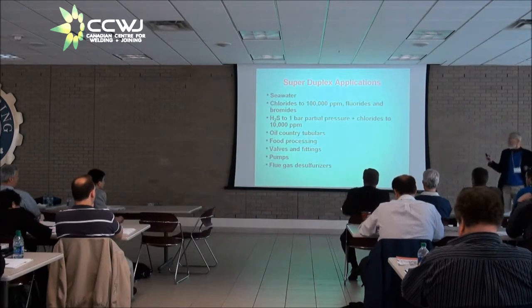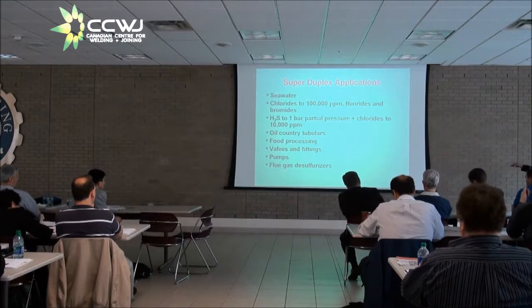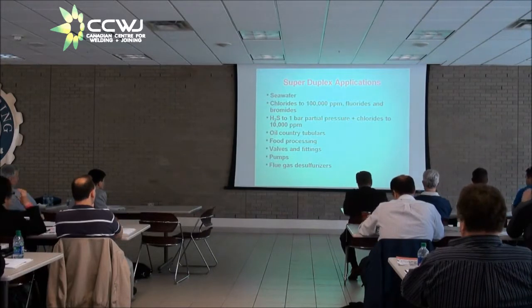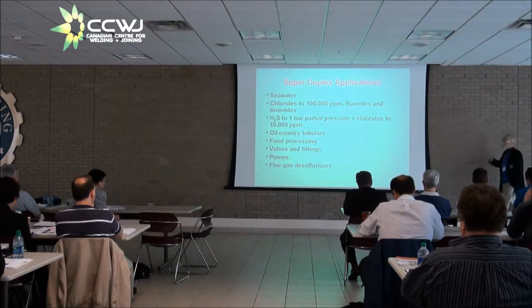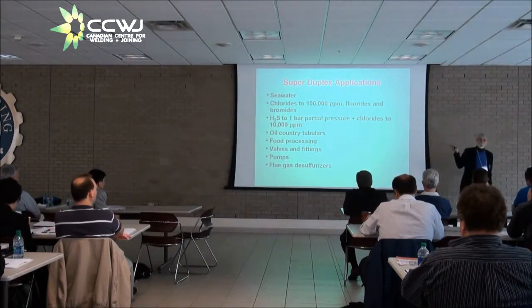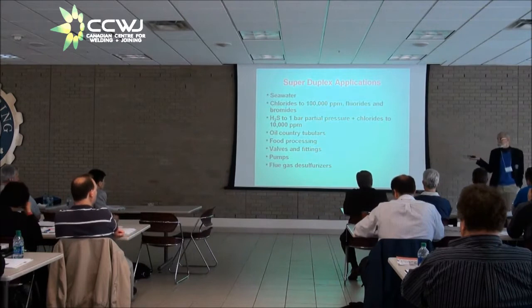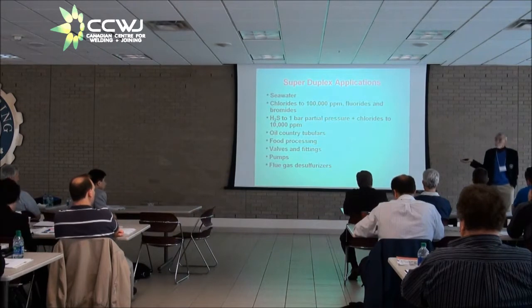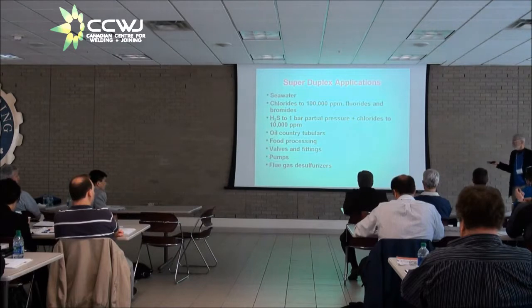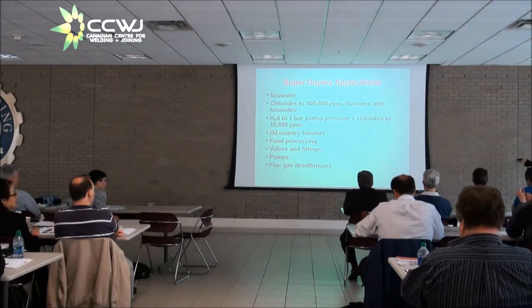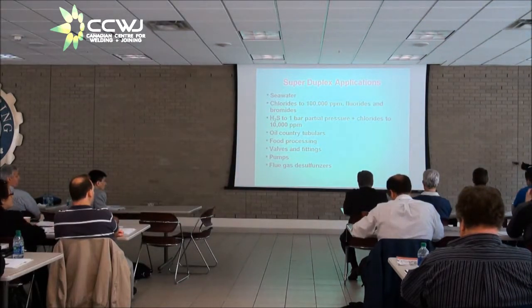One of the interesting applications for the super duplexes is the flue gas desulfurizers. Flue gas desulfurizers have high temperature areas and low temperature areas. You don't use super duplex in the high temperature part of the flue gas desulfurizer. We use it in the low temperature part, and it's quite resistant to the acids and the chlorides and whatnot that exist in that pipe.